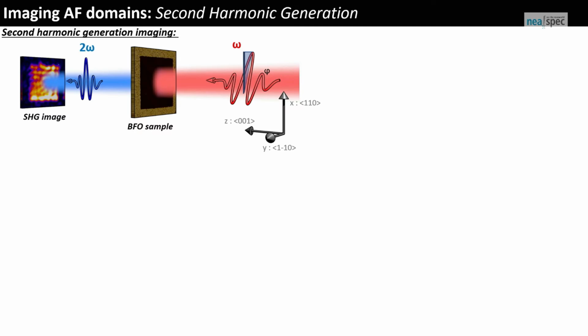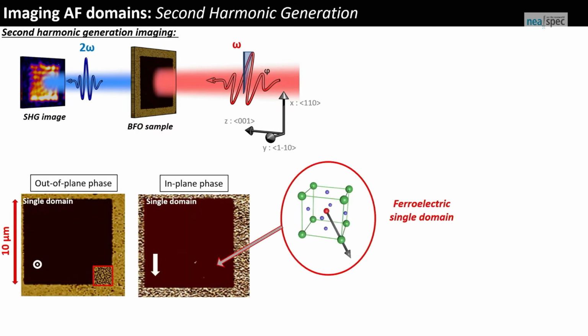you shine a light at omega on the samples, and under certain conditions, typically symmetry-breaking conditions, in space and time, the samples can generate light at twice the frequency, and if you collect it and analyze it, you can get a certain amount of information. So this is what we did, but obviously now you see why we need the near-field optics, because the first